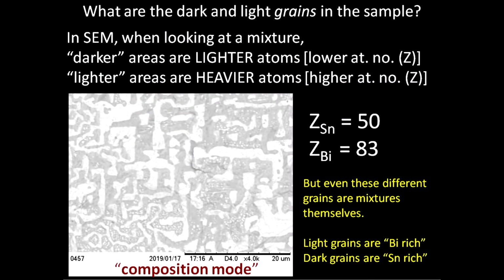So what are the dark and light grains in this sample? And here's the thing about this setting on a scanning electron microscope, an SEM. It actually turns out that the darker areas are lighter atoms. So they have a lower atomic number, and the lighter or brighter areas in an image are produced by predominantly heavier atoms, or atoms with a higher atomic number.